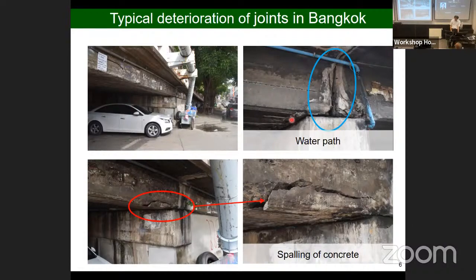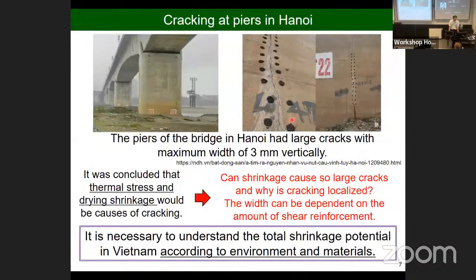That is the issue. Another issue is from Vietnam. My colleague explained that they have a big crack in the center of the piers of a bridge, and they are wondering what the reason is. The crack is 3 millimeters, very big. That is a big problem. Their conclusion is that this is thermal stress and drying shrinkage. But the question is, can shrinkage cause such large shrinkage cracks, 3 millimeters, and why is it so localized?